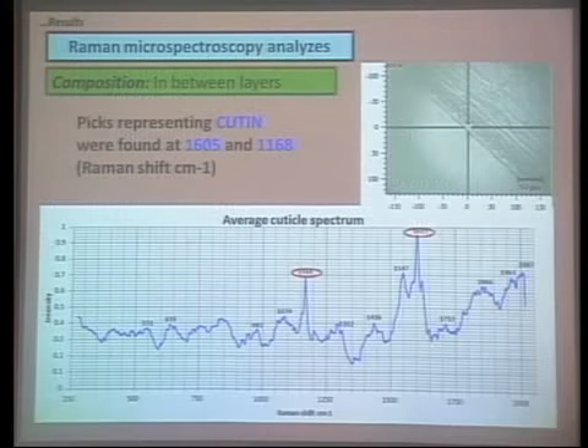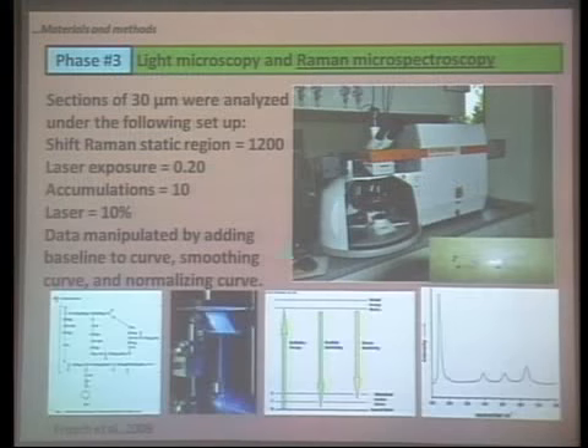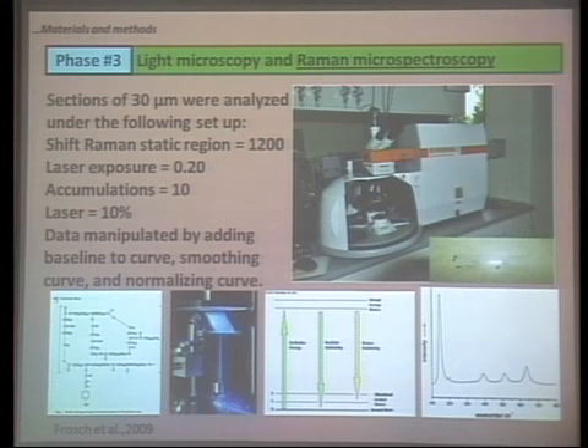So the results that we got, here was our example. We aim our laser. Sorry, I forgot to explain this part here. This was our settings for the Raman. We had it to practice to see what were the best settings. Our Raman region for the components that we were evaluating was 1200. The time of exposure that the laser is open on our sample was 0.2 seconds. It was 10 times the laser was reflected in our samples at only 10% of the total potential energy that the laser can emit.